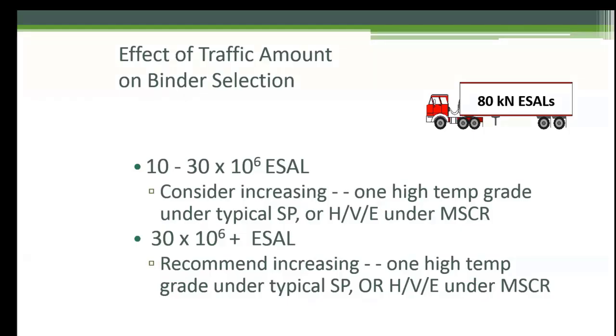And that's why you see a lot of problems, usually of stability, will first occur in an area of starting and stopping, whether that's a stop sign or a signal light. And so the original PG binder protocol was that if I had extremely high truck traffic, out of my total ADT, average daily traffic, a large percentage was truck traffic, I would do what's called a grade bump. I'd take that 58C, for example, and bump it up to a 64.